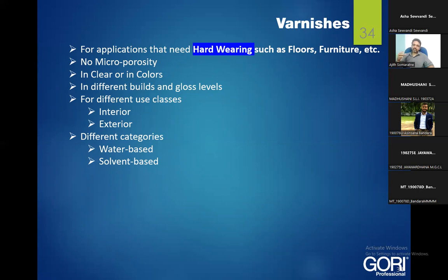But in the Sri Lankan industry, actually, there are some dislikes for varnishes because in early stages, some people used varnishes in exterior applications and got many defects. So bad experience. So now in the Sri Lankan market, most people don't like varnishes. But in some cases, varnish is the only solution, especially for interior floorings. But you have to remember that varnishes don't have a microporous feature. So when we use a varnish in an exterior context, we have to be careful, because if we cover all six sides of the wood using a varnish, then the wood will crack very easily with time, with temperature changes. Right? So we have to take care of that.